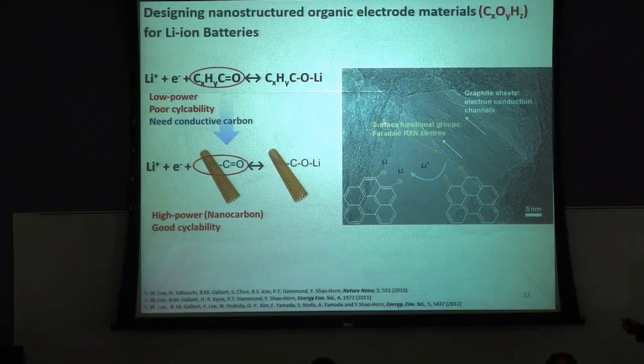So this is a schematic of the functionalized multi-wall carbon nanotubes. We oxidized the surface of the carbon nanotubes. If we look at the surface, there are many oxygen functional groups on it. As you can see, we have the sp2 conduction wall over this multi-wall carbon nanotube. This can be a good electron conduction channel. And on the surface, there are many oxygen functional groups that can react with lithium ions and store 1 electron. This is the basic design principle of the functionalized carbon nanotubes.